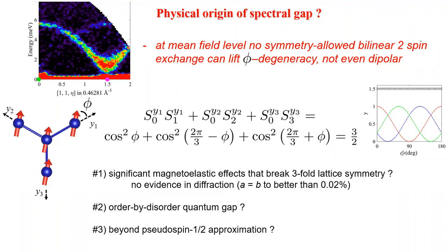So the other possible mechanism could be order by disorder, because of course this is a mean field calculation, but the crystal structure doesn't have continuous symmetry; it has only discrete symmetries, and so one can think that the spin wave spectrum, and the harmonic part of that, the half h bar omega, would then depend on the spin orientation, and that could potentially select several directions for the moment plane.